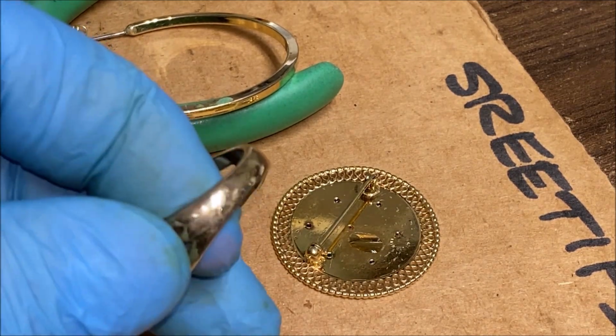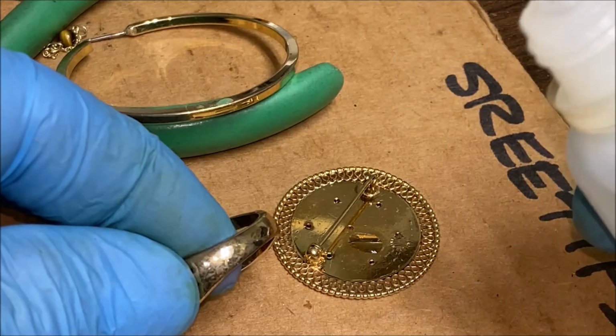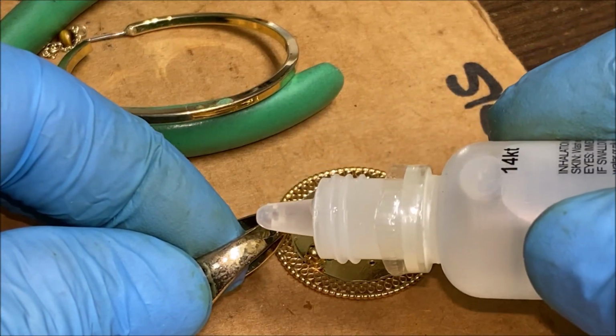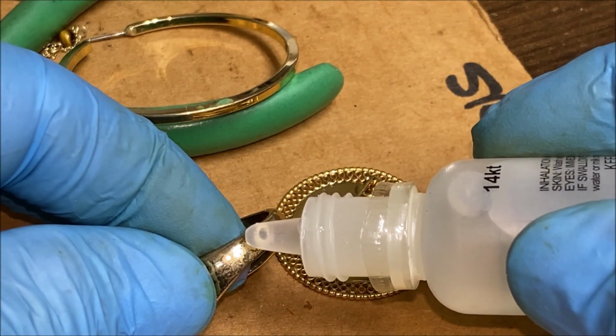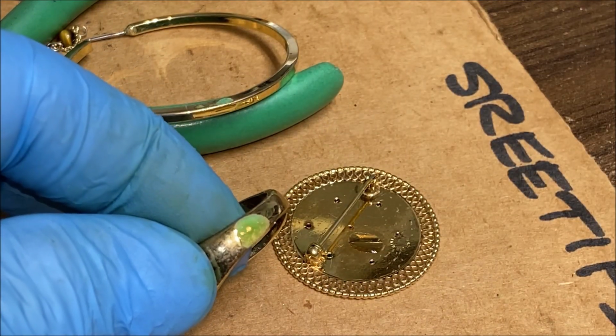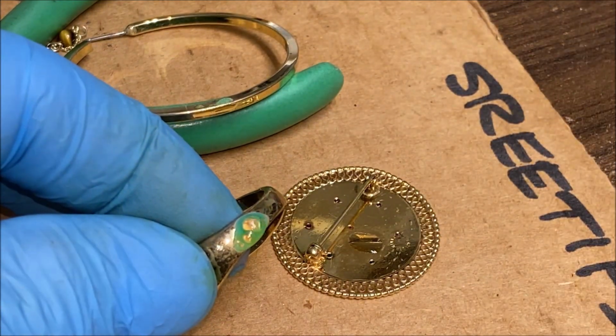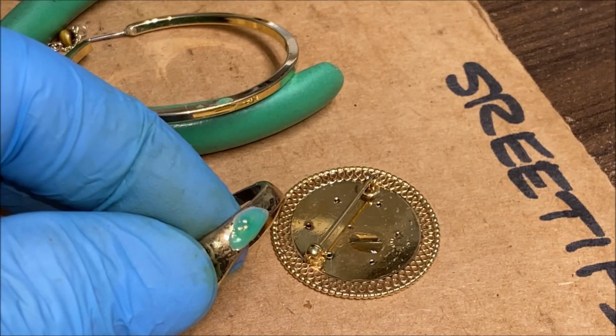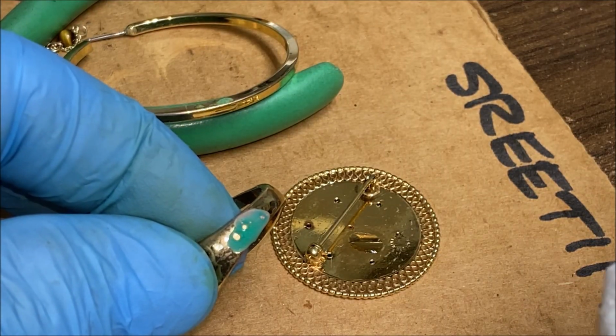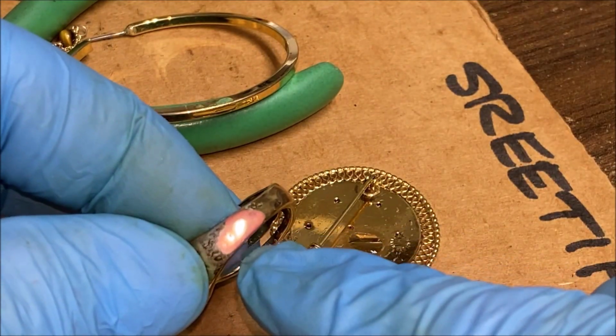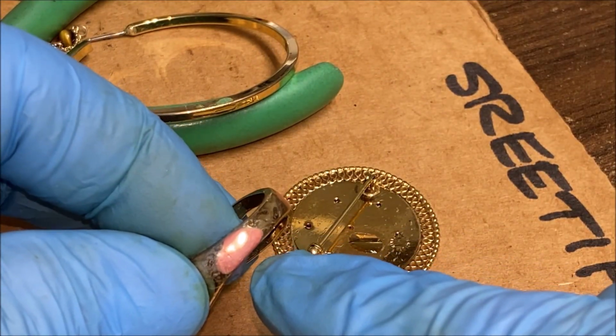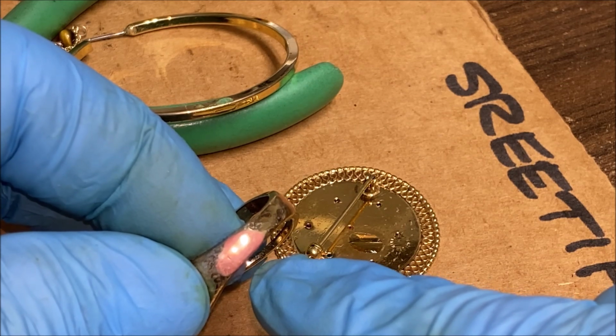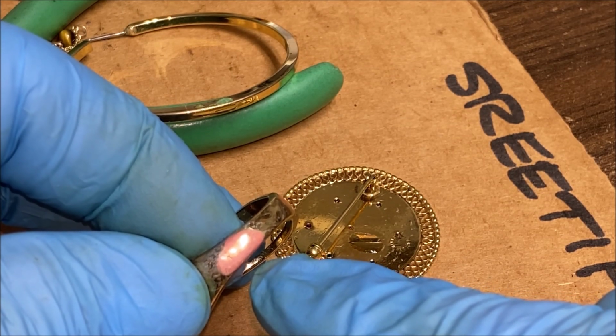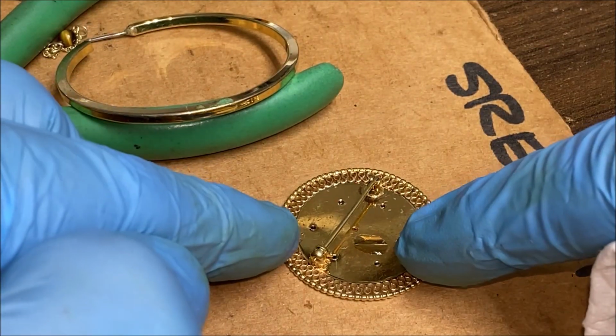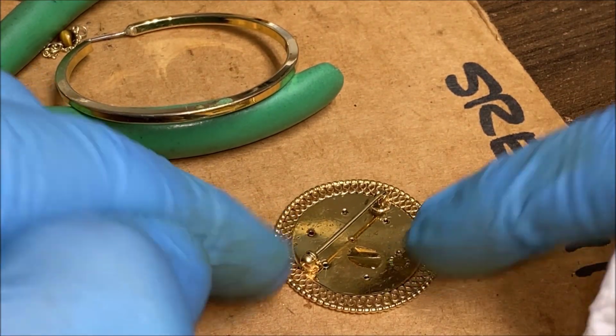However, if we've got a piece of gold plated material like I've got right here, we put some test acid directly on the piece, and you'll notice that we get an almost immediate reaction. It starts bubbling, turning green, and that's because there's only a few microns of gold plating on here. The acid will eat through it almost immediately and reveal the base metal underneath. Notice that our gold filled material is still resisting the acid.